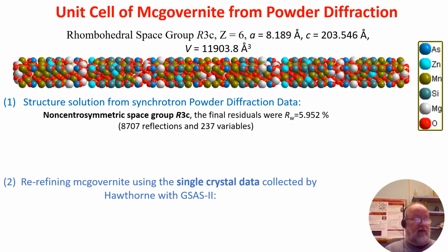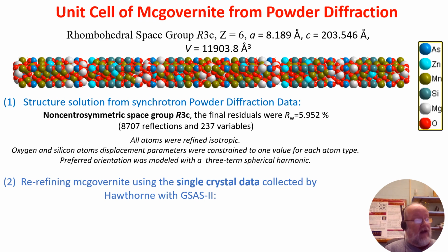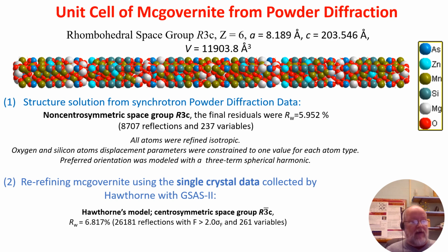Now realize, we solved the crystal structure from powder diffraction data. And what does that mean? All our atoms had to be isotropic. We didn't have enough data to actually model anisotropic displacement parameters. The oxygen atoms, we had to constrain all displacement parameters together. The silicon, we had to constrain them all together. And that's probably because the pseudo-symmetry was causing us problems, gave us a lot of correlation, and we couldn't refine them adequately. And we also had to refine some other properties that you don't in single crystal, like preferred orientation.